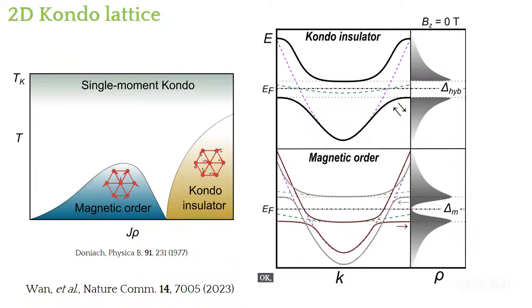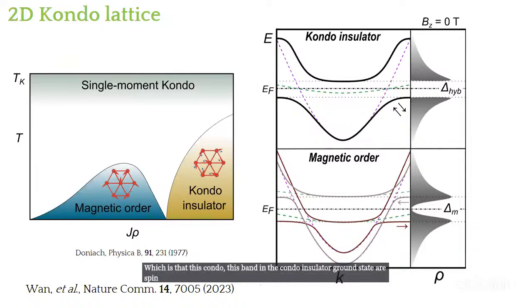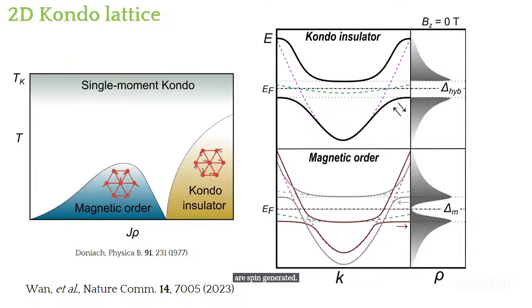But you can see that this is true as long as you don't apply a magnetic field. There's a key difference between these two band structures, which is that these bands in the Kondo insulator ground state are spin degenerate. Okay, so we have the two flavors, whereas in the magnetic order, they are spin polarized.